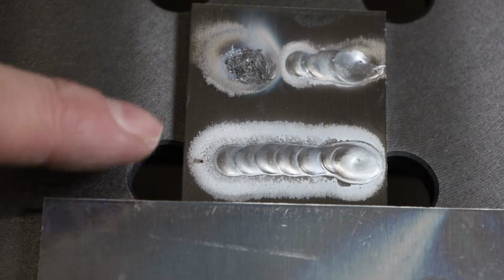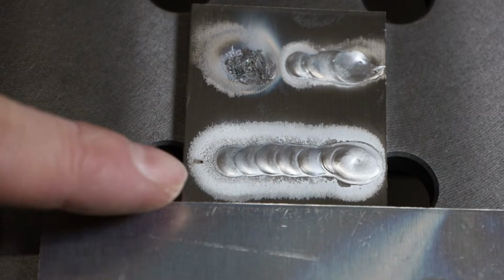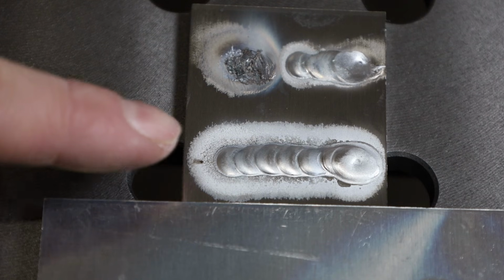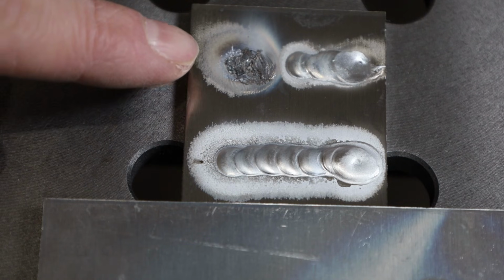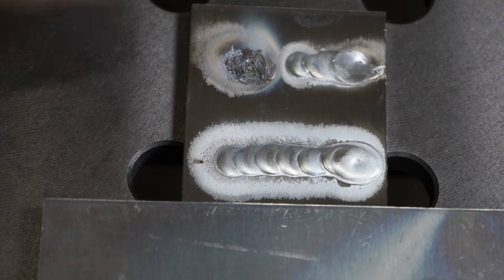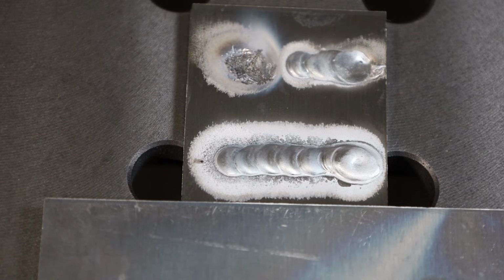And that can come for a couple reasons, but one of the main ones is flowing too much shielding gas. So in summary, you want to have it high enough that you get a nice clean weld, but not so high that it rattles your brain and etches too much of the material. So that's what you're looking for on gas flow rate.